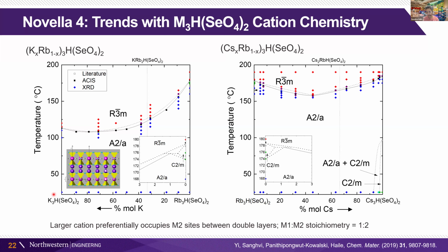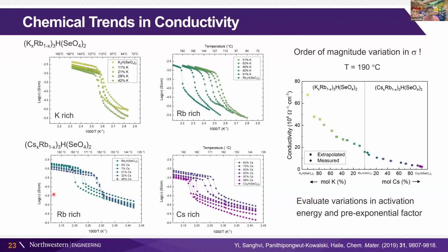In the case of the rubidium to cesium side, that's a little more of a fixed transition temperature, and we have a slightly different phase behavior where, in fact, at close to 50-50, we have a decrease in the transition temperature, which gives us advantages to some extent for the overall application. The conductivity we measured here, which was the other goal, was to really understand how the conductivity changes with the substitution of these cations. And what we found in this case is that having the smaller cation increases the conductivity at a given temperature.